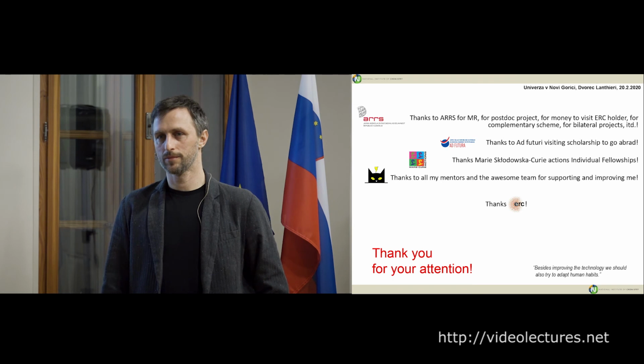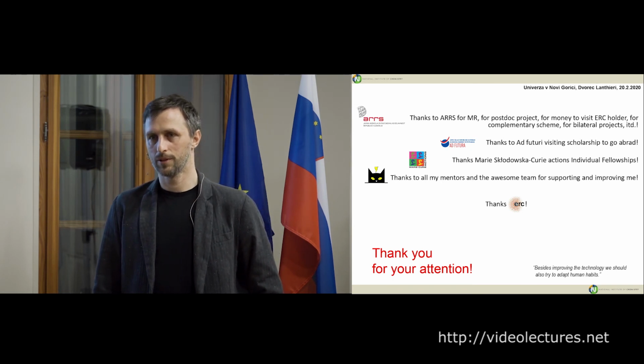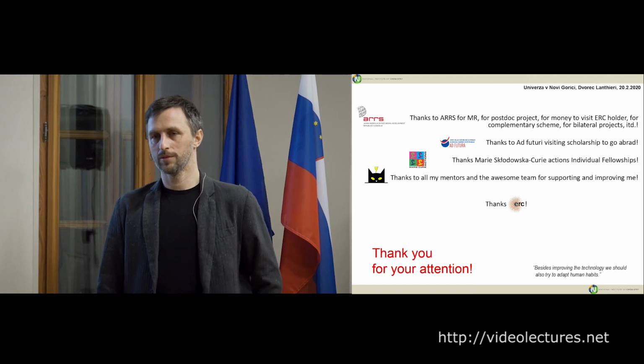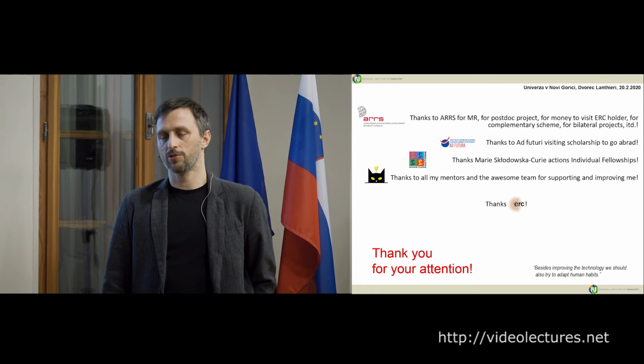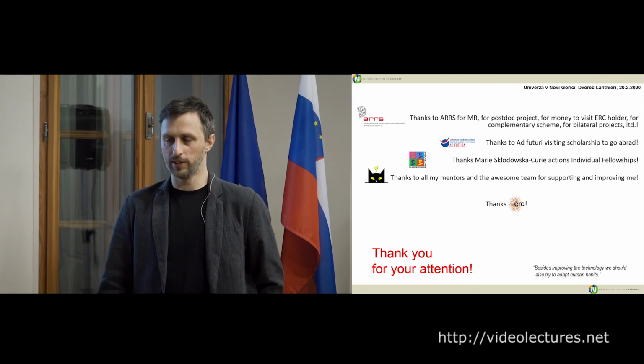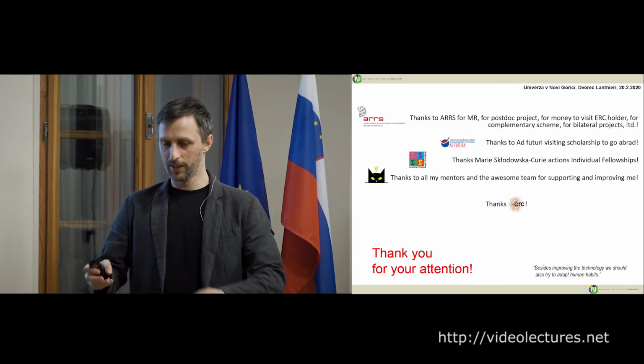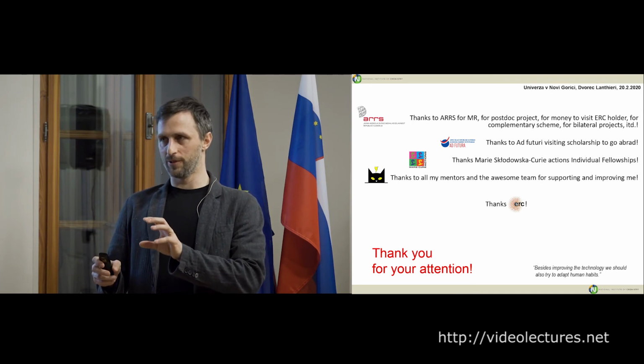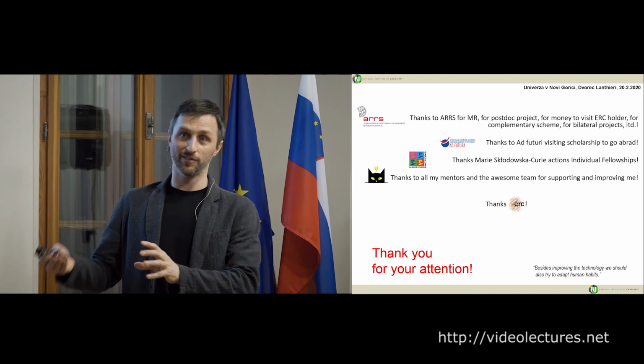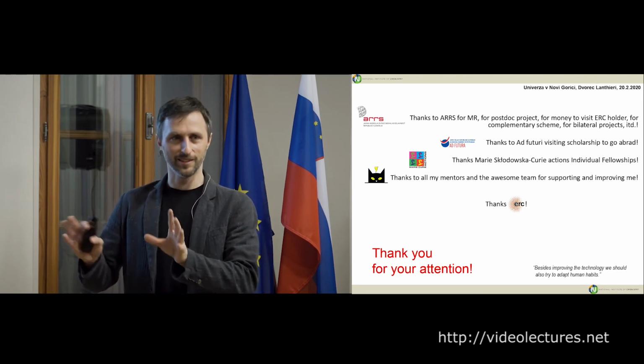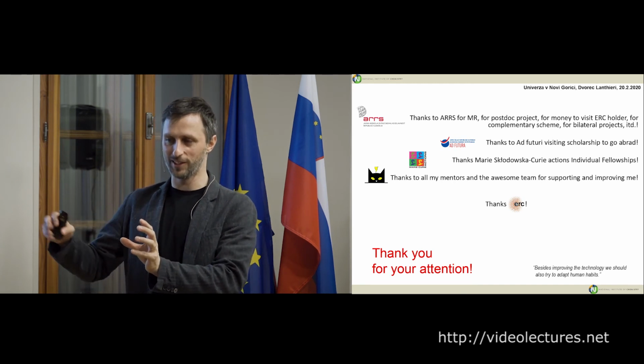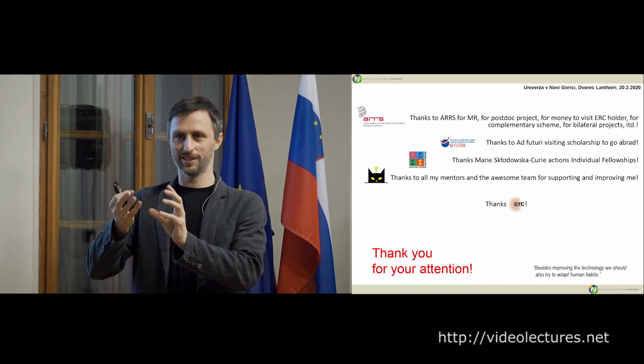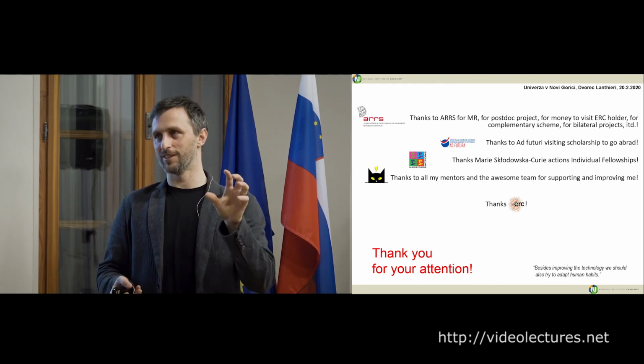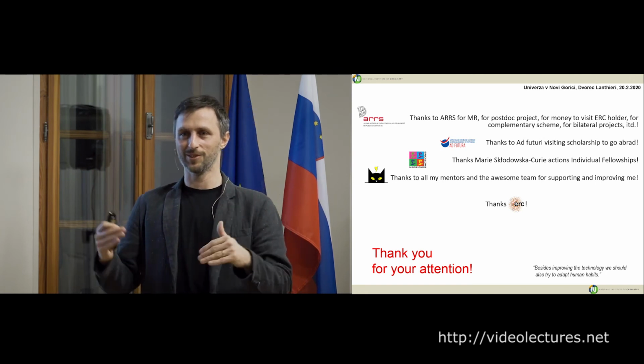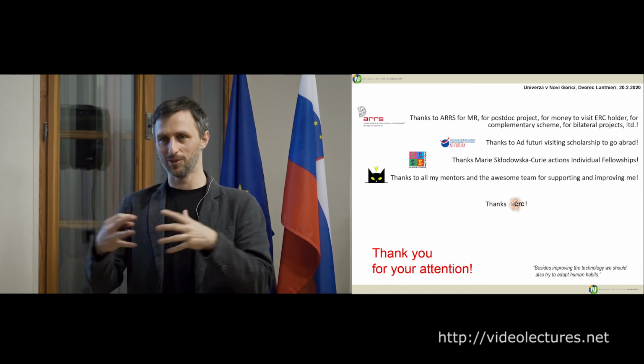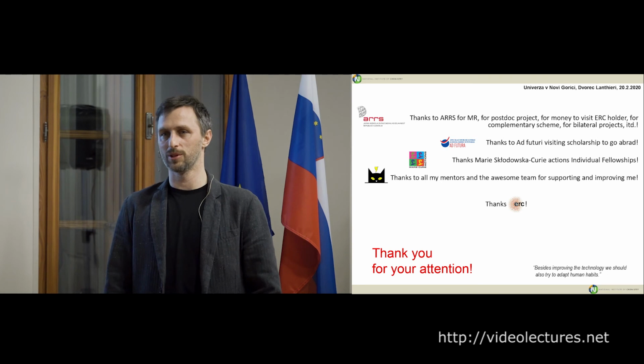Commercially, usually sold is mixed oxide, ruthenium iridium oxide. How do you think the combination of the two is not better than a single one? It's better, it shows higher activity. I think this is one of the ways to improve. There are two ways. You can have iridium oxide, which is not as active, so you add ruthenium to make it more active. Or you can also say, you add iridium to ruthenium to make it more stable. So iridium is more stable, ruthenium is more active. By combining these two and oxidizing them, you stabilize them.